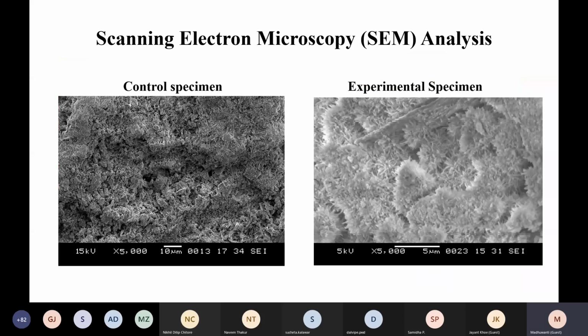So now to further prove that these results are due to deposition of calcium carbonate in the microvoids of the cementitious materials, we subjected control specimen of the 28-day curing period and experimental specimen to scanning electron microscopy analysis, SEM. These are the graphs, and you can clearly see in the experimental specimen, there are crystals of calcium carbonate.